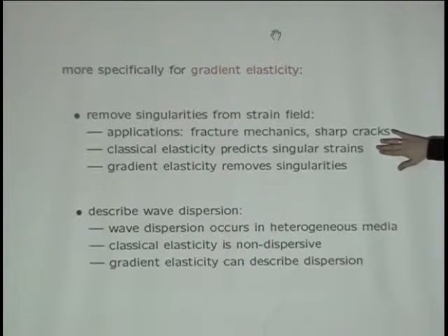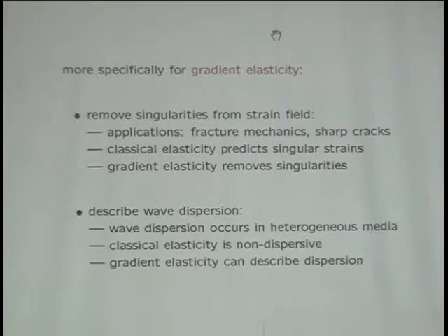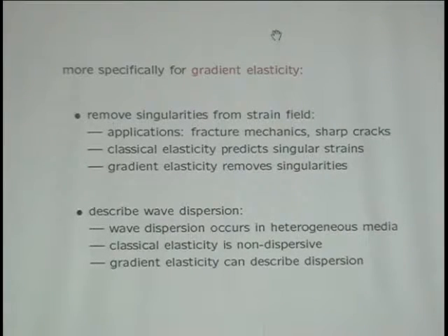So classical elasticity obviously predicts singular strains at sharp crack tips, and you can remove those by using gradient elasticity. And probably less relevant for this audience, in dynamics people want to describe wave dispersion, where every wave number travels with its own speed, but that's maybe for another day.